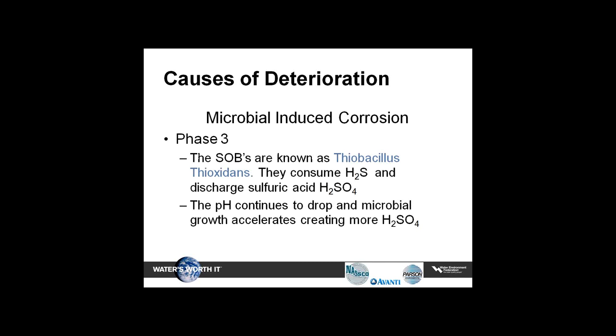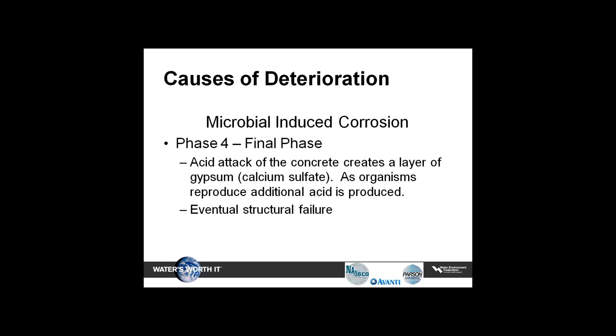Phase 3, these SOBs are known as Thiobacillus thiooxidans. They consume H2S and discharge sulfuric acid. The pH continues to drop, and the microbial growth accelerates, creating more and more acids. Phase 4 is where we generally see the corrosion. The acid attack of the concrete layers creates gypsum. These organisms continue to reproduce, additional acid is produced, and then there's eventual structure failure.